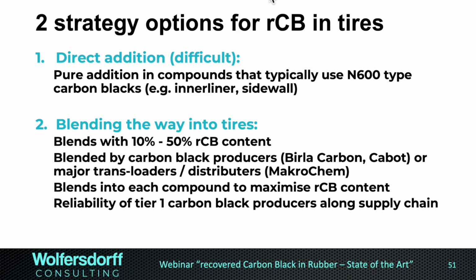also the transloading company MakroChem, doing blends of furnace carbon black with a defined recovered carbon black content. This is very similar to the biofuel you can buy at the local station. Here in Germany we have an E5 with 5% biofuel, E10 with 10% biofuel. For example, Cabot has presented a 550 carbon black with 10% recovered carbon black. So it's blended by carbon black producers, major transloaders, distributors, and MakroChem.